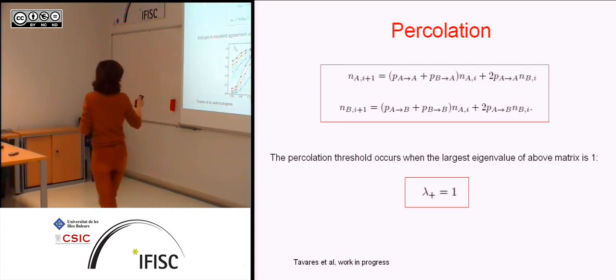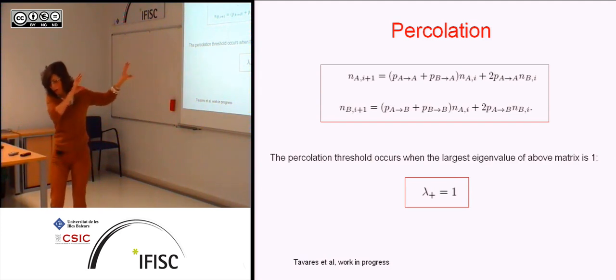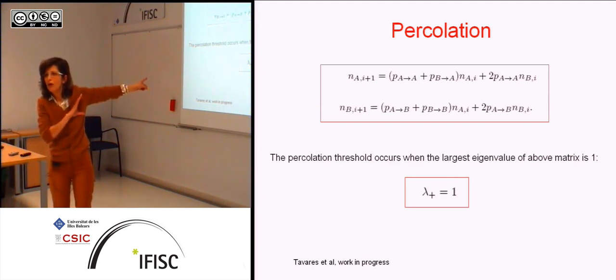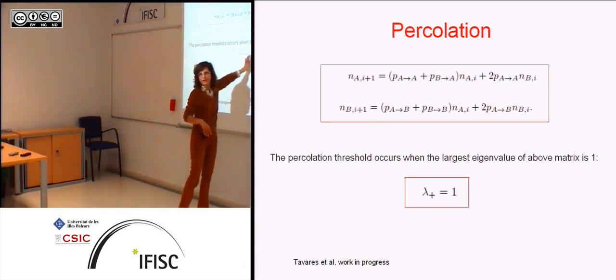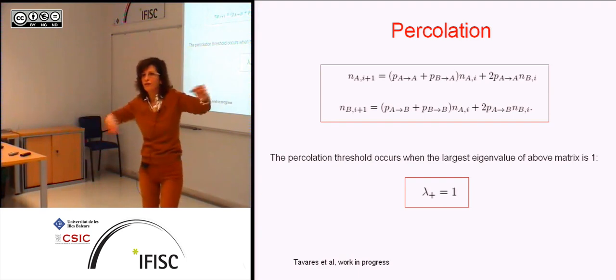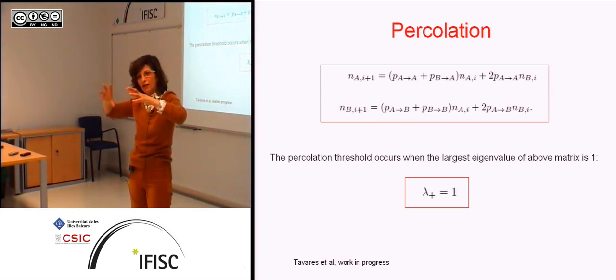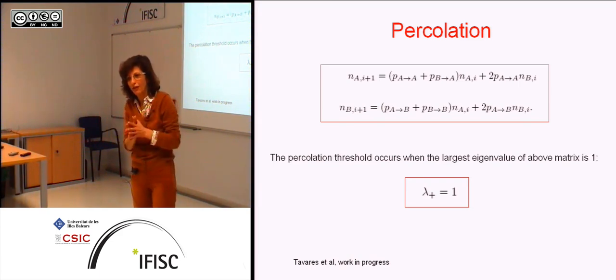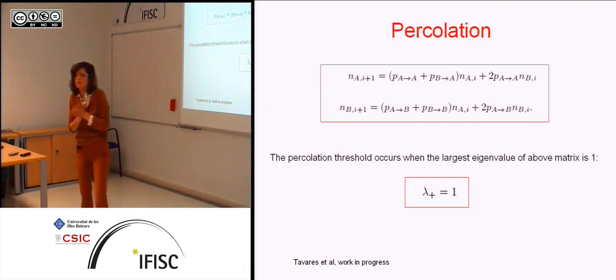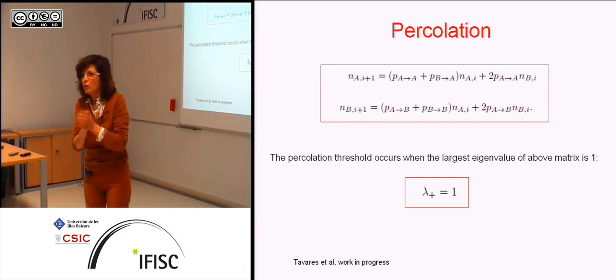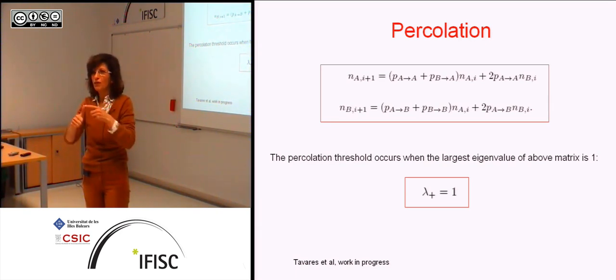The following trick is close to percolation. If you look at the equations, the clusters are big, and they are dominated by the larger eigenvalues. There are two eigenvalues, and one is bigger; for the cluster you sum the series, and there's this eigenvalue to some power, and so of course the distribution is going to be dominated by the largest of these eigenvalues. So the idea is to assume that the system is described effectively by some model which has a bonding probability and a number of sites of functionality, which is determined by matching the moments that we can calculate exactly to a model with all equal sizes and with the same moments.